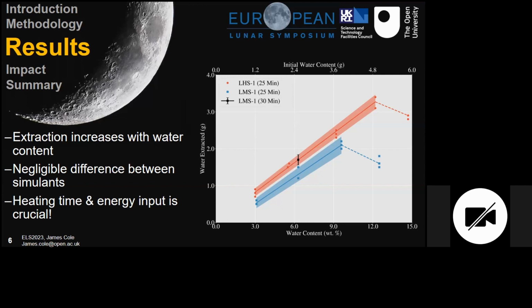And then if you go along the x-axis, what you can see is that as you add more water, unsurprisingly, you get more water out. However, the really surprising thing we found is that near the saturation points of both simulants, the extraction actually drops. This really wasn't what we were expecting, and I'm going to talk about that in the next slide. But really overall, what we found is that the heating time and energy input is crucial to maximizing your water extraction.